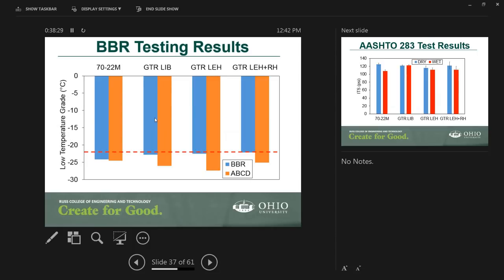Now, in terms of testing, I'm showing both BBR and ABCD. Again, in all cases, it met the minus 22 criteria. A very important thing is that the BBR has a problem in testing modified asphalt binders, whether it is polymer or GTR, whenever your modifier has a percentage of more than 4%. These are some of the issues with the BBR. So if you're evaluating a highly modified asphalt binder, you might have some issues. What we noticed is that there are differences between the ABCD PG grading and the BBR, specifically when it comes to a highly modified binder.